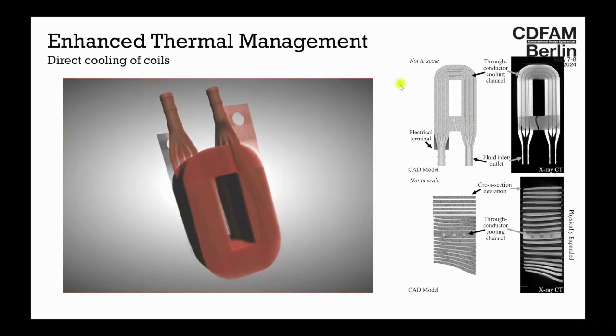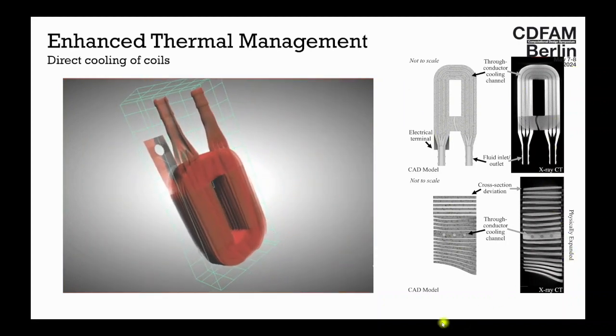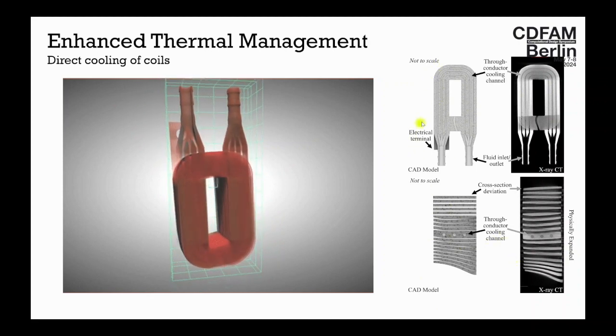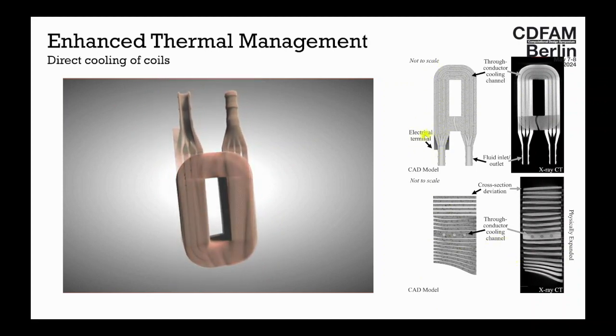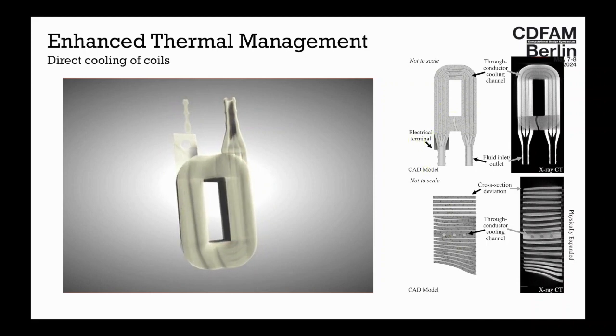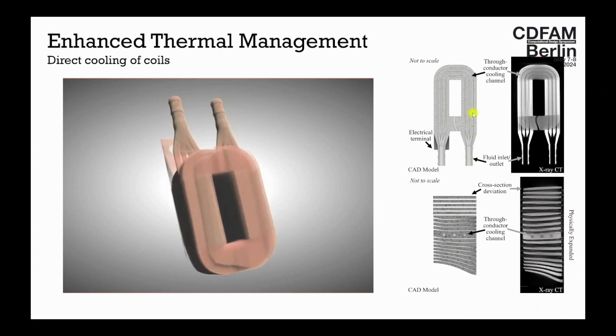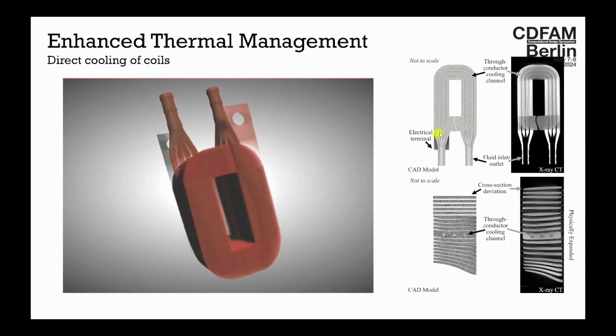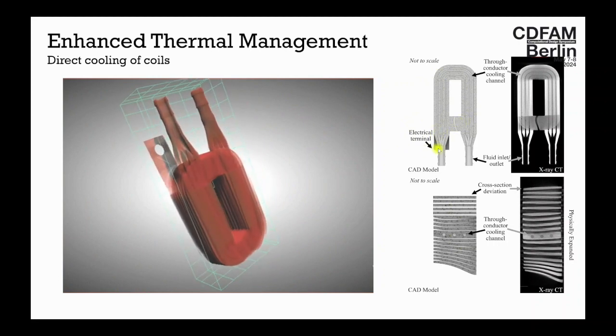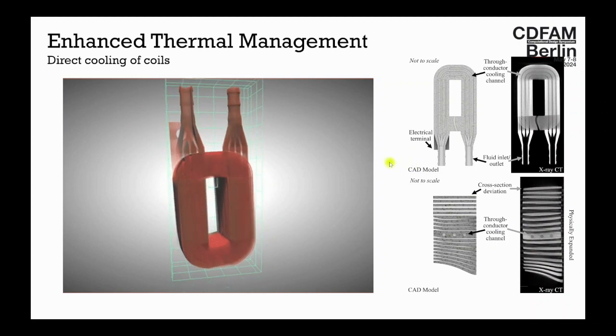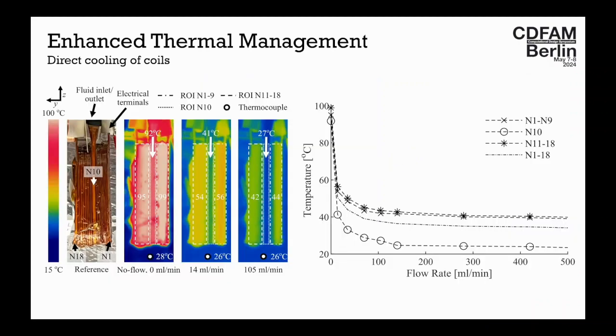Now, as you can see, on the right-hand side, these are X-ray CTs, and it faithfully represents pretty much the CAD geometry. It's really impressive because those cross-sections of those channels are only 1.5 millimeters. And we were able to evacuate them. We've tested this and proven that it works. Now, this was created using parametric boundary represented CAD. However, you can see that when we start playing around with the geometry, some of these features start to fail, and that's a serious problem for us. Nevertheless, it works extremely well, so even for very, very modest flow rates, so a small amount of fluid being pumped in there, you can significantly reduce the temperature.